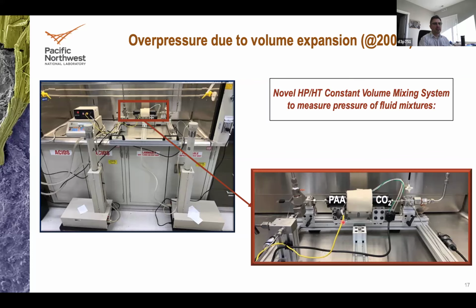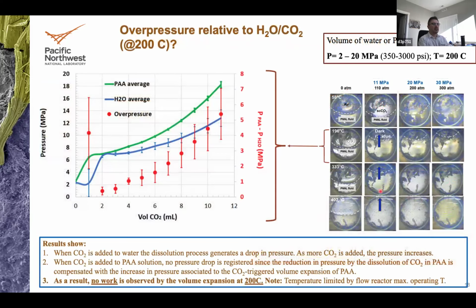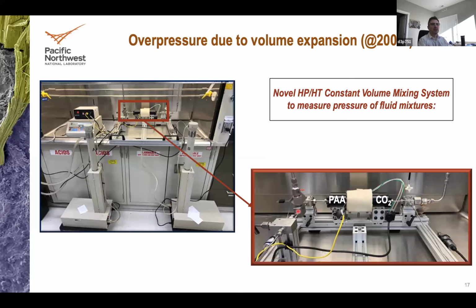We did this at 200 Celsius, again limited by the operation temperature of the reactor. But what we see is the following, and this is very important. We do see an overpressure relative to the water CO2, because we did water CO2 3 times and polymer solution CO2 3 times, 3 experiments each time, hence the error bars. What we observe is that when we do water and we open the valve at 6 megapascal of CO2, we get around 1 milliliter of CO2 in, and then we close the valve of this reactor. This is already closed. We have a constant volume with constant mass of CO2 added, about 1 milliliter at 6 megapascal.